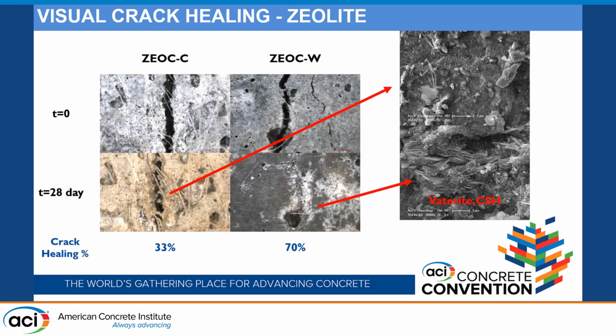When we compare calcium and sodium exchange, potassium exchange could react very fast. In this study, we used clinoptilolite zeolite, which contains 2.5 to 3.8% potassium oxide and calcium oxide, which also affects the reactivity of the zeolite. We observe vaterite and CSH gels in the SEM and FTIR analyses of the sample without bacteria cured in water. Moreover, the crack sealing in zeolite samples cured in nutrient medium was found to be less efficient. It can be related to the nutrient medium containing an additional calcium source and having a pH of 9, which might affect the cation exchange in the zeolite and reduce its reactivity.